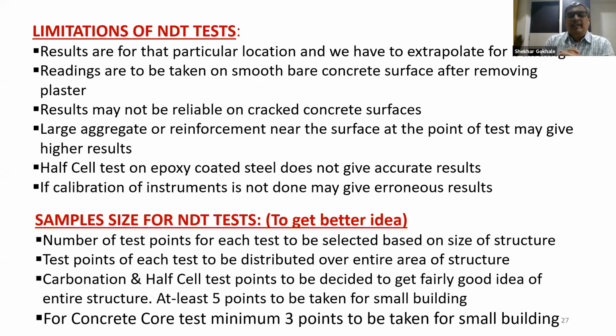Then readings are to be taken on a smooth bare concrete surface. It should not be taken on a plaster surface. If plaster surface readings are taken for rebound hammer or ultrasonic pulse velocity, then we are likely to get erroneous results. Even if the concrete surface is cracked, readings taken on that surface will be erroneous.